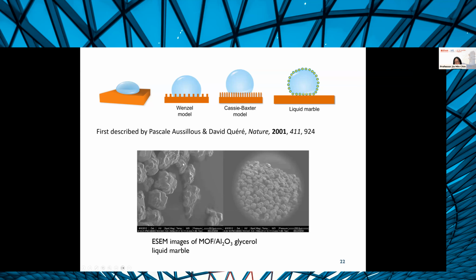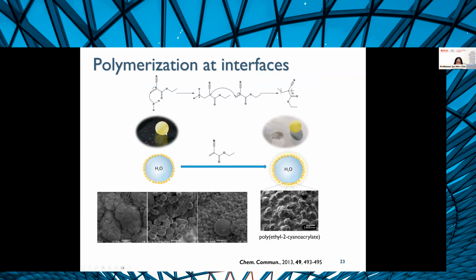And so we thought, maybe we could learn to encapsulate these liquid marbles by using some kind of interfacial polymerization. So what we did was expose these liquid marbles to essentially just super glue, or ethyl cyanoacrylate. This molecule is very easily polymerized. You just need water, for example, and it starts to initiate a polymerization and it just goes. So when we had this in a chamber with some superglue fumes, we found that over time, you start to see polymerization. These little nodules are the polymer of superglue, and these are the MOF alumina composite particles. And if you leave it long enough, you start to really cover everything with this layer of polymer.